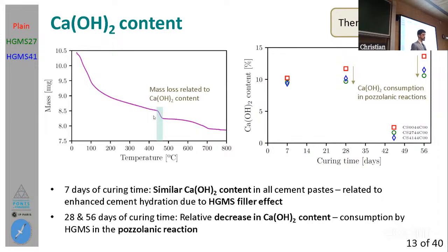And this difference here, which is highlighted, is related to a mass loss that corresponds to the amount of calcium hydroxide that we have in the cement paste. So with that, I was able to obtain the content of this hydration compound product at 7, 28, and 56 days of hydration, of curing time, with the red being the plain cement paste, the green the cement paste with HGMS27, and the blue the cement paste with HGMS41.